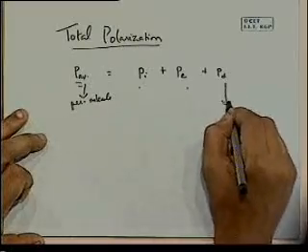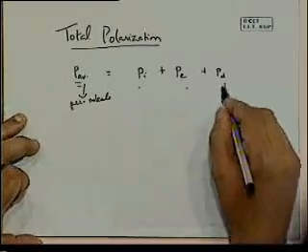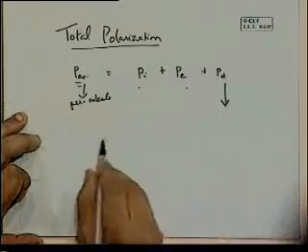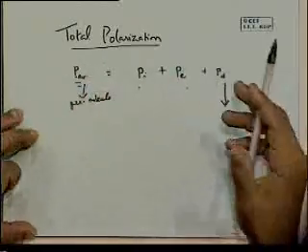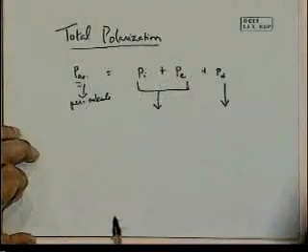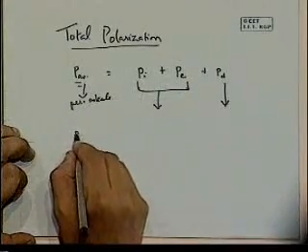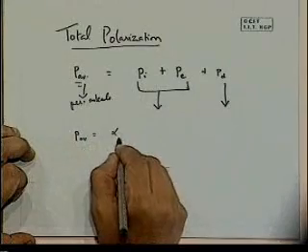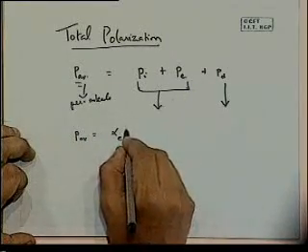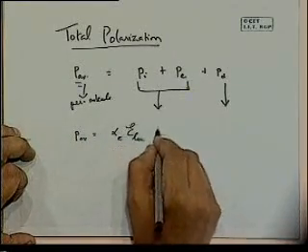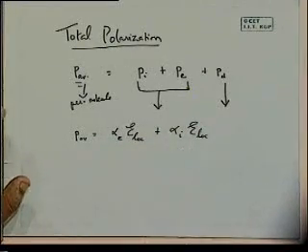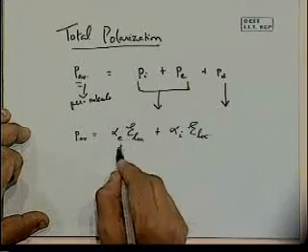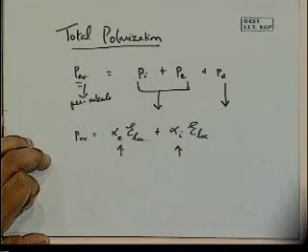Now, in this form, I said we simply cannot get a simple relationship with the Clausius-Mossotti equation to know the relationship between P average and between epsilon r and alpha. So, as long as we are dealing with only these two, we can come up with a simple relationship, namely that P average is equal to alpha E, the electronic polarizability, times the local field, plus alpha I times the local field. We treat only these two. And I have expressions for these in terms of the Clausius-Mossotti equations.